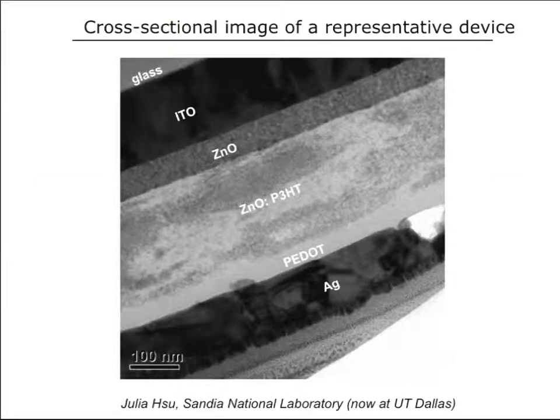So just to give you an idea of the general structure for such a device, this is an inverted device, cross-sectional TEM, imaged by Julia Hsu, who's now at UT Dallas. So here's our ITO, a zinc oxide, typically about 20 nanometers. The bulk heterojunction, which in this case is using zinc oxide as an electron acceptor, but as I mentioned, this is normally a fullerene. And then this positive electrode on top, which we can sometimes put in a buffer layer of PEDOT to help extract the holes.